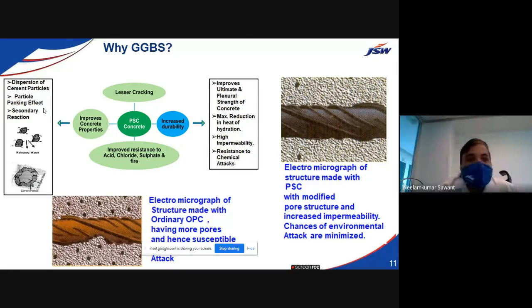You can observe on the left hand side, this is one of the reinforcement bars, which is red in color and rusted. And if you see the concrete cover, so many black dots are there, which is called porosity. This is the electromicrograph we have obtained with concrete cast with OPC, and you can see more pores. Whereas if I'm using PSC cement, or a mixture of OPC plus GGBS in my concrete, these pores will decrease by about 10 to 15%, and it improves the ultimate compressive strength as well as flexural strength of the concrete.